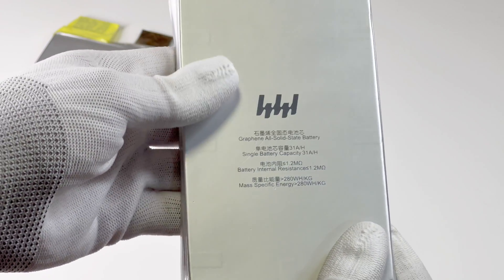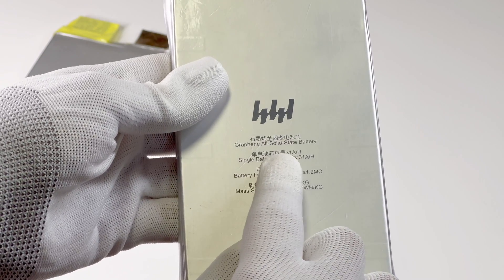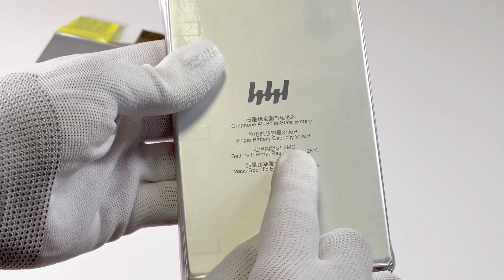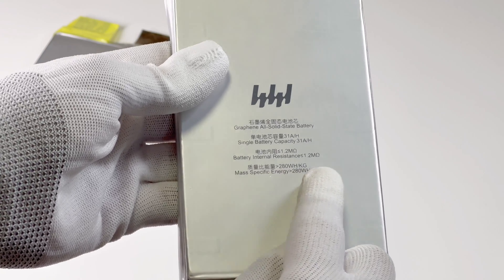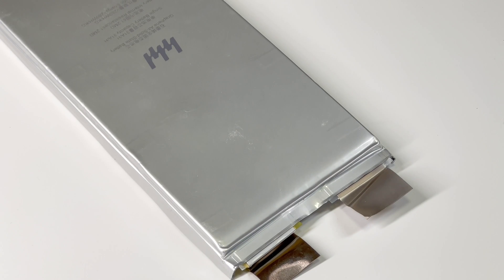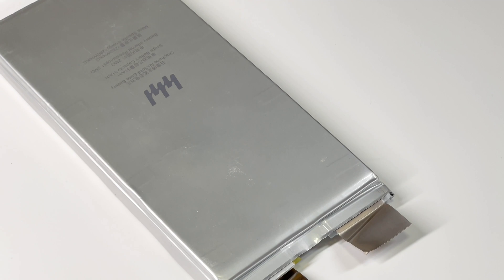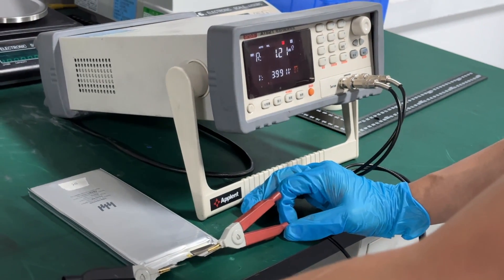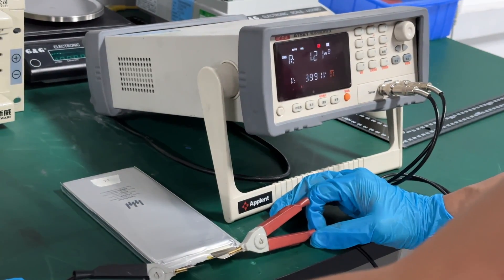It is called a graphene all-solid-state battery. The single battery capacity is 31Ah. The internal resistance is less than 1.2mΩ, and the mass-specific energy is more than 280Wh per kg, while the lithium-iron battery is generally between 200–260Wh per kg. So its energy density has exceeded the industry standard. After testing, its internal resistance is only 1.21mΩ, which means it has excellent discharging performance.